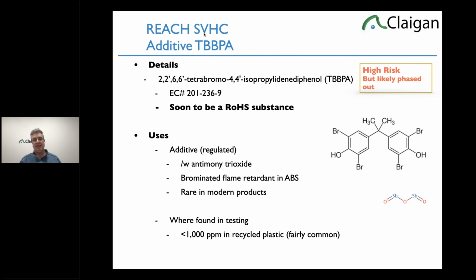It's not this. And also, you get declarations from suppliers. There'll be tetrabromo bisphenol A diglycidyl ether resin. That's also a totally different chemical. That's tetrabromo bisphenol A attached to a diglycidyl ether on both sides, actually. Also not tetrabromo bisphenol A. But there are a lot of things that use the name, like BPA epoxy is not BPA either. It's BPA diglycidyl ether epoxy, often BADGE. It's a very different chemical. There's a BPA in it, but it's not BPA. And so this will also soon be, well, I'll say soon, not that soon. If the new REACH substances were controlled by the European Chemical Agency, this would be a REACH substance by now.